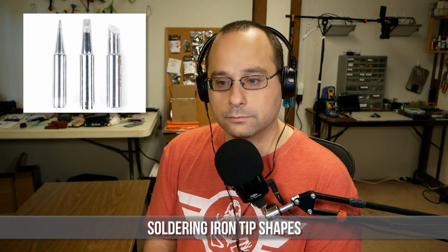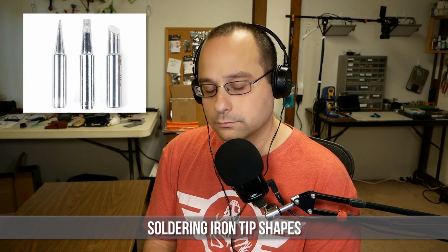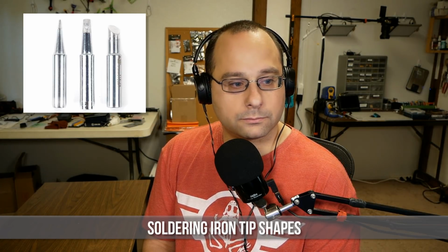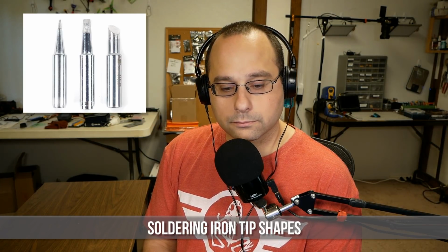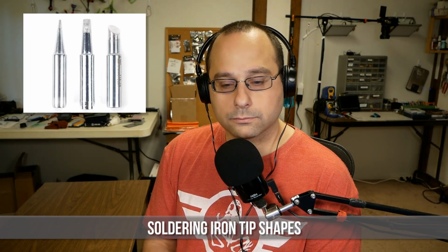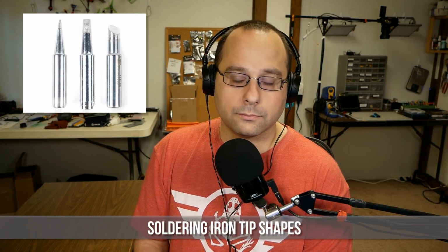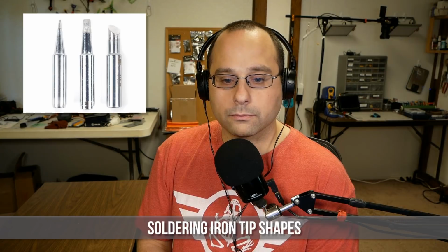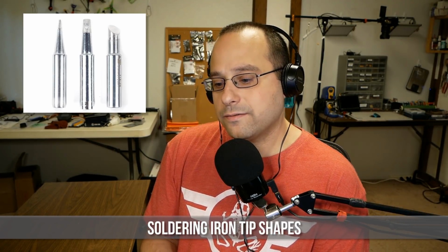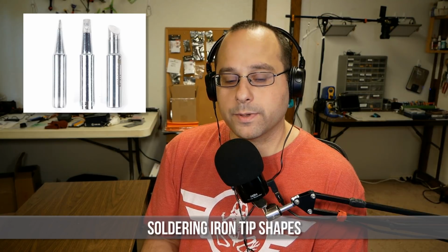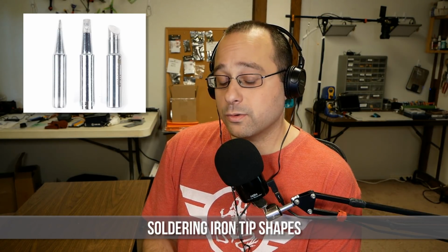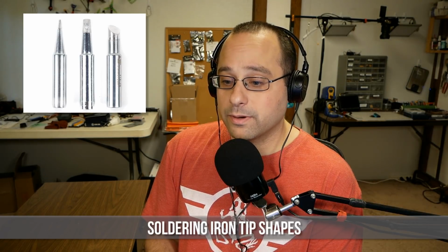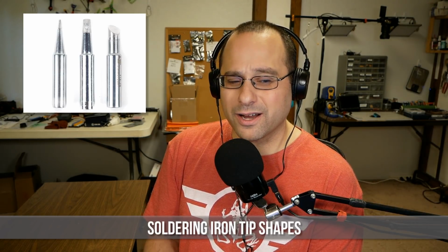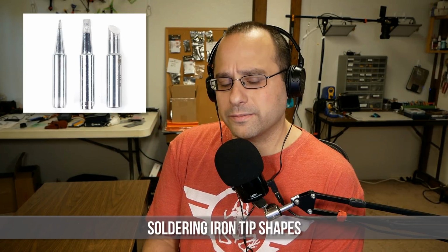Sure. The advantage of the bevel is you get more surface area. The more surface area you have on the tip, the more you're going to heat up your parts. So if you're soldering wire, for example, you'd want to use a bevel tip and probably go as wide as you can on the bevel tip. And the disadvantage, I think, when I've used those is the bigger bevels are heavier. They have more thermal mass, especially with a weaker iron. I think a bevel can make up a little bit for your weaker iron. Would you agree with that or disagree?